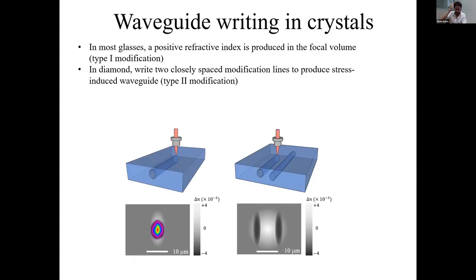And so our idea is to closely space two damage lines together to form a stress in between them. Through the stress optic effect, the idea is to form a positive refractive index change in this compressive stress zone between the two lines. This is what's known as the type 2 modification.